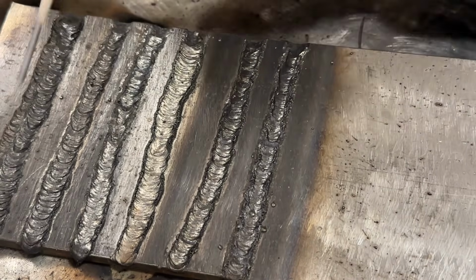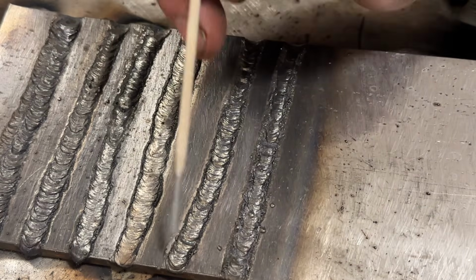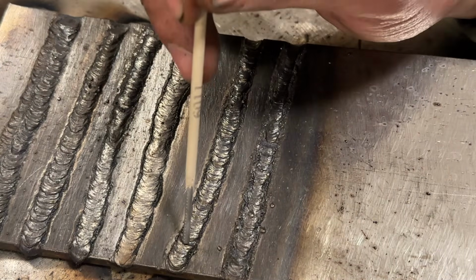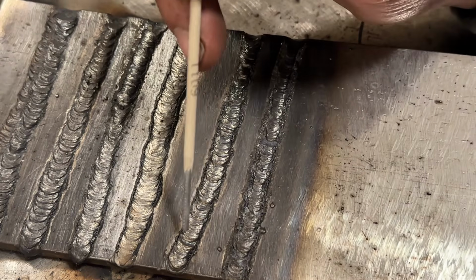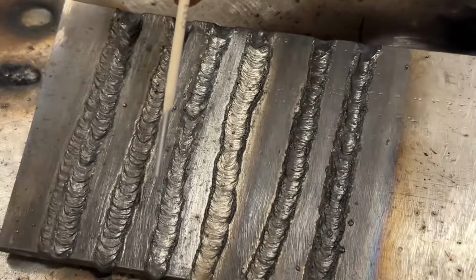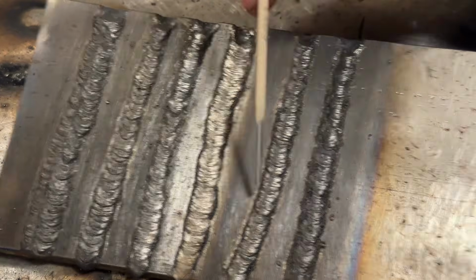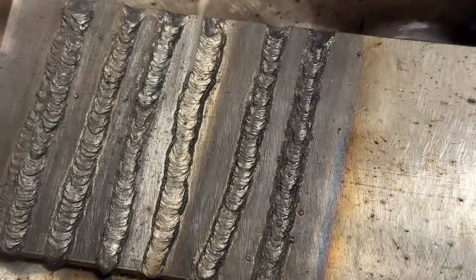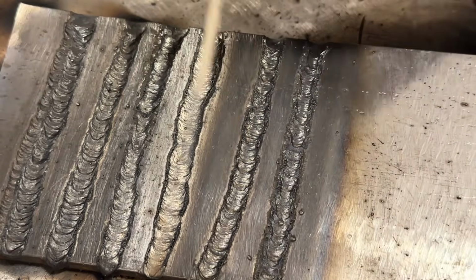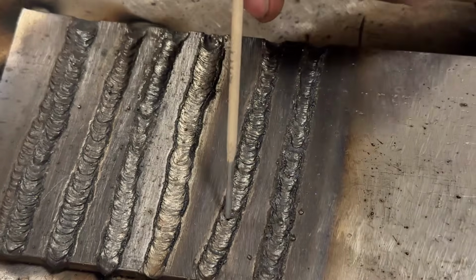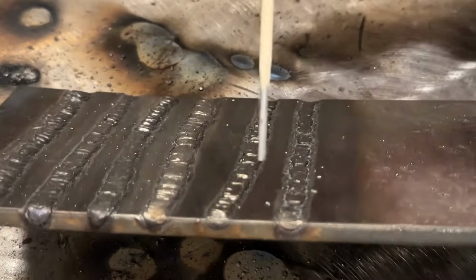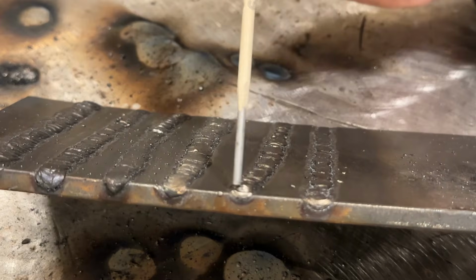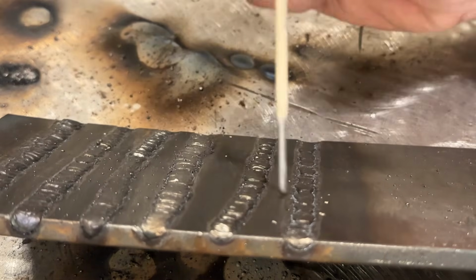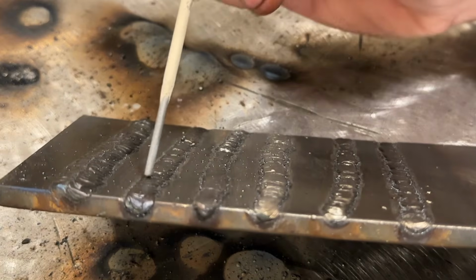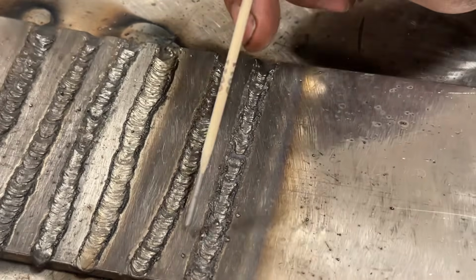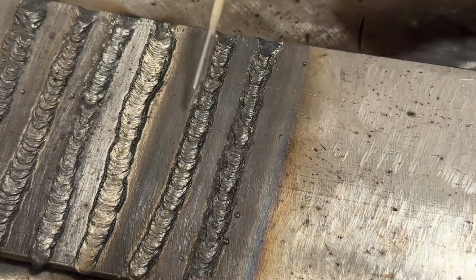All right, so a couple things here. Now, I had a higher arc force setting here. I did cram the rod in a little bit, but my travel speed was a little bit higher than what it was here. Width, see how it's a little bit narrower? Another indication of your travel speed is the height of it. You can see the start's a little bit cold, pretty tall, flatter, okay? Not a big deal. So this ran pretty good even though I was cramming a lot of rod in.